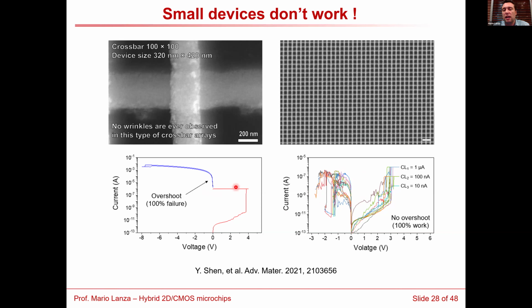The reason is that this current limitation is introduced through the semiconductor parameter analyzer. And this system has a delay of around 70 microseconds. And 70 microseconds is enough for having 1 peak of current here, which you cannot see, but is there, and breaks our device, okay? This happens randomly, but even in these devices where it did not happen in the first cycle, maybe it happens in the next cycle.